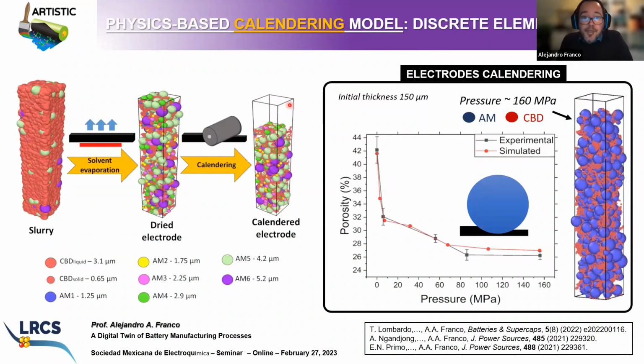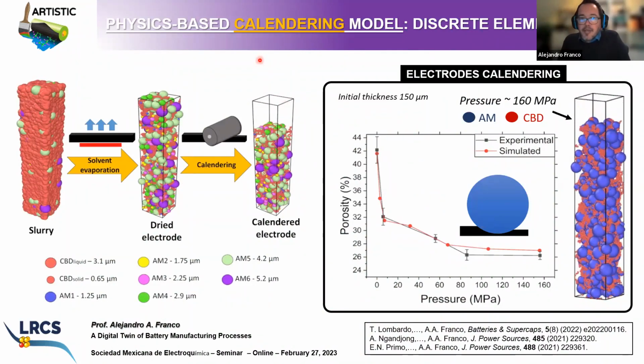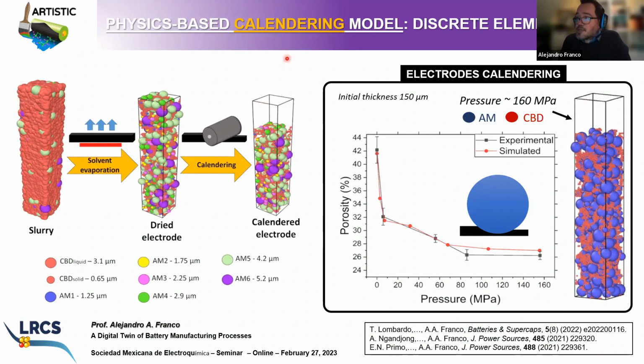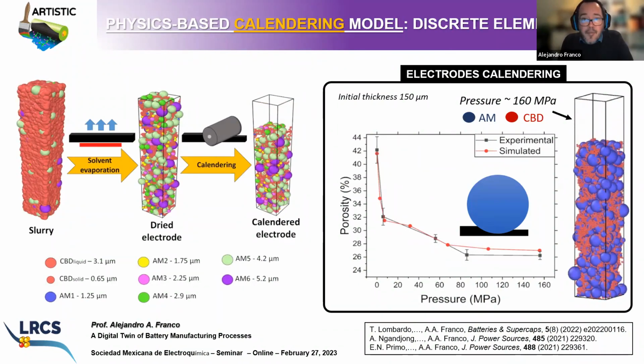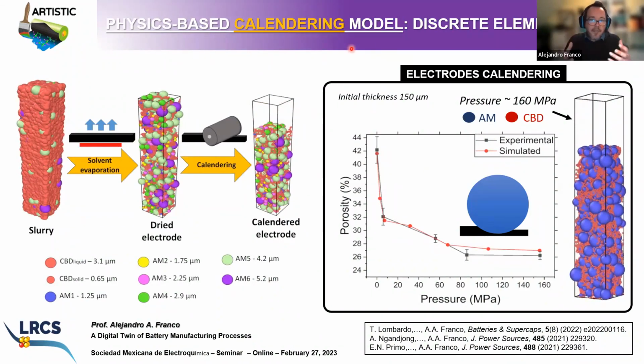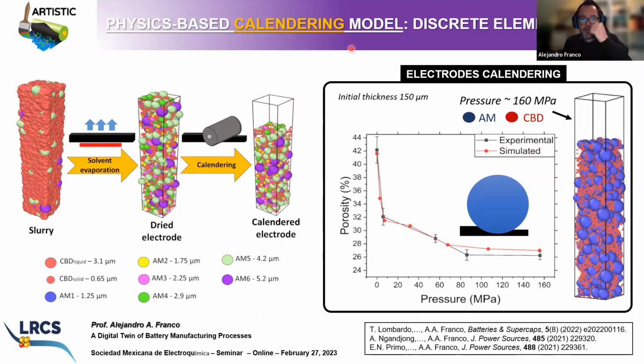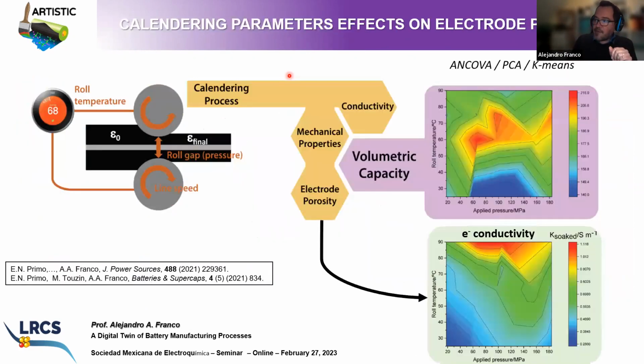How do we model this calendering process using the physics-based approach in the ARTISTIC project? We use the discrete element method, which is a kind of particle dynamics or molecular dynamics method for mechanics. Here we describe interaction forces between the active material particles, between the CBD particles, and the active material particles. And then we simulate the effect of compression.